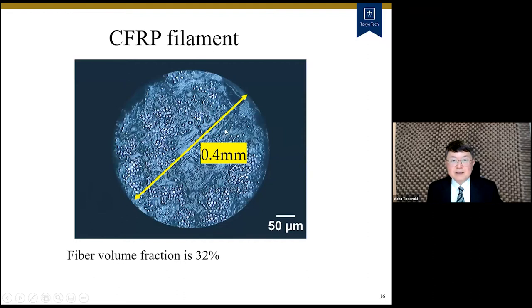And this slide showed the cross-sectional view of the CFRP filament. The diameter is 0.4 millimeters, and you can see these white circles. This one is carbon fibers, and the fiber volume fraction is approximately 32%. And you can see this is comprised of the carbon fibers and polyamide 6 resin.